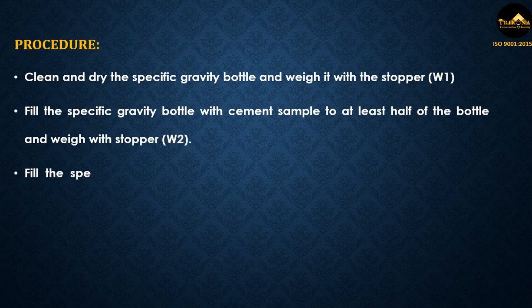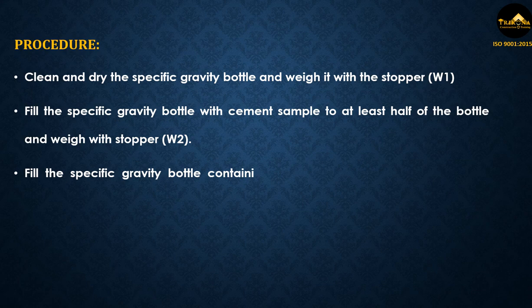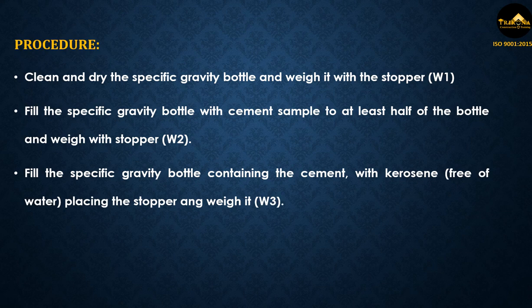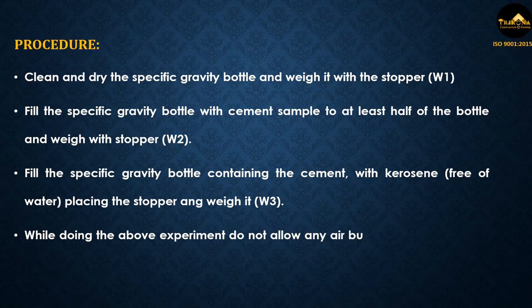Fill the specific gravity bottle containing the cement with kerosene free of water, place the stopper and weigh it (W3). While doing the above experiment, do not allow any air bubbles to remain in the specific gravity bottle.